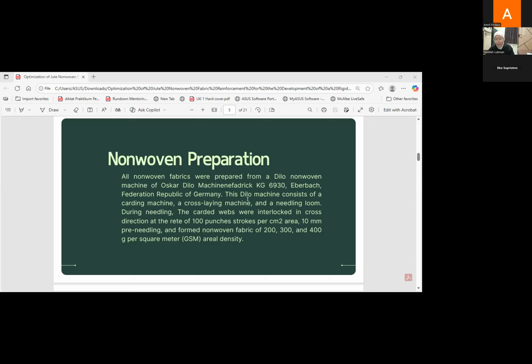In this paper, before they make the composite, we must make the jute non-woven first. All non-woven in this paper was prepared by a Dilo machine, a machine from Germany. This Dilo machine consists of a carding machine, a cross-layering machine, and a needling loom. During needling, the carded webs interlock in the cross direction at the rate of 100 punch strokes per square centimeter area, 10 millimeter pre-needling, and form non-woven fabric of 200, 300, and 400 gram per square meter GSM areal density, or grammage.